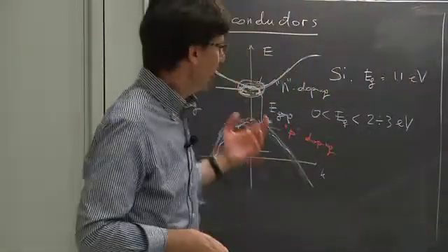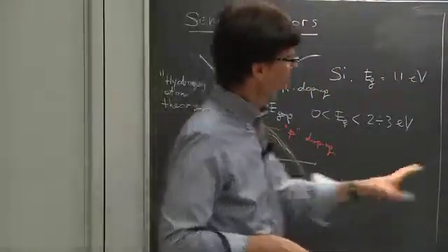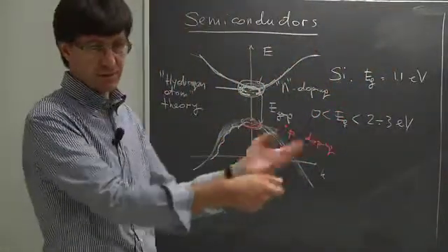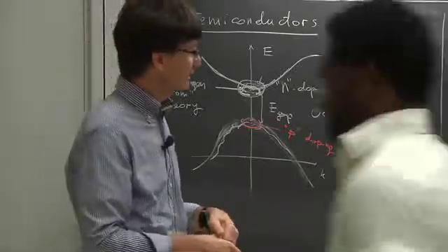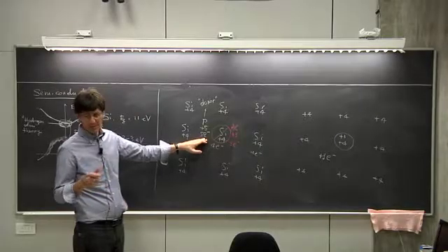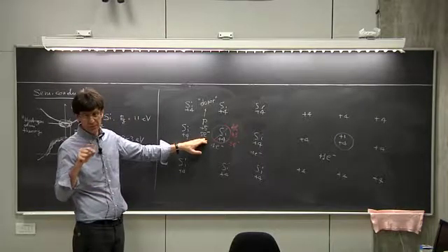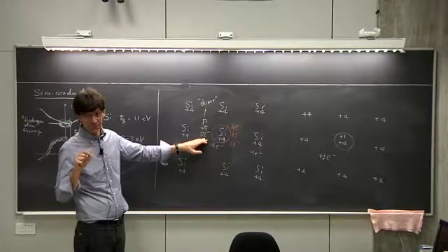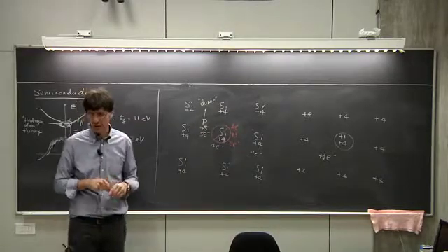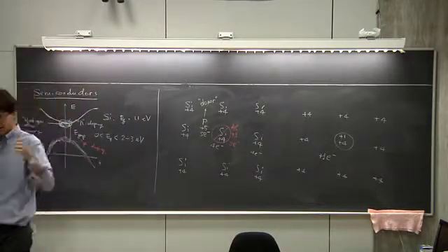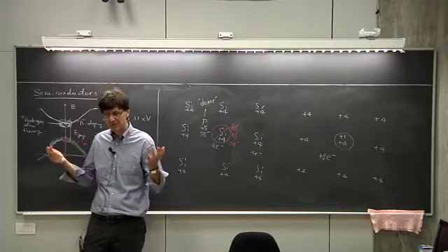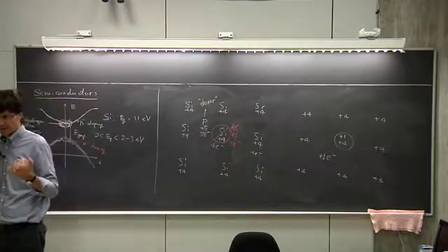Realistic amounts of doping, the ones that are interesting from a technological point of view, the ones that you find in any transistor, in any electronic device, are of the order of 10 to the minus 6, 10 to the minus 7. So 1 out of a million or 10 million silicon atoms is a phosphorus or something else. So the concentration is small, but not extreme. We're not talking about a single atom in the whole crystal. We're talking about 1 out of a million, which out of 10 to the 23rd atoms is quite a lot.